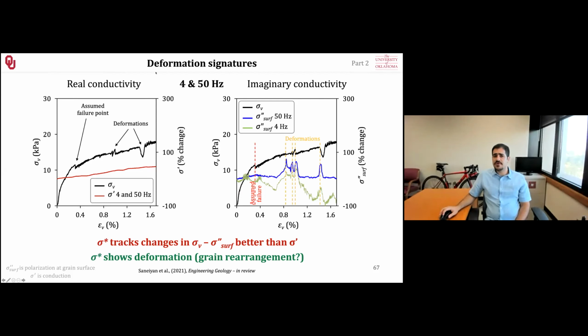We did another experiment, this time just to measure the deformation. So we had a soil sample that didn't show that much of a failure like the other one, that sharp drop, but kept showing some peaks and ups and downs in the stress signal. And you can clearly see that the imaginary conductivity also changes at both low and high frequencies with the same sort of peaks, like the inverse of the peaks we are seeing in here. This is interesting. It shows you that not only are we able to show the failure, we also show any rearrangement of the grain during this compression.